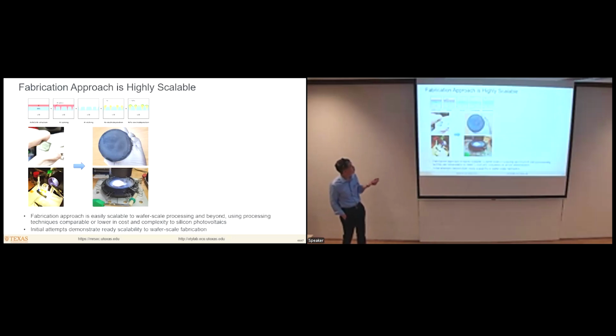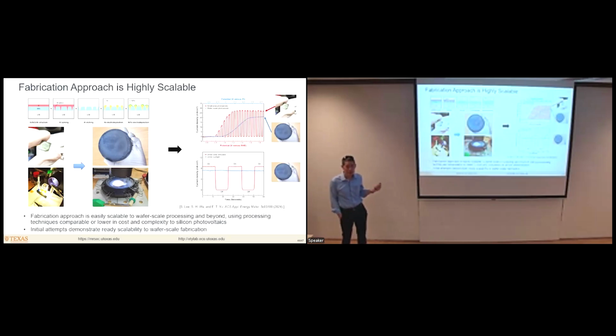So we were able to go quite easily from making devices that are kind of this size, which is what is typically reported in literature, to doing this on full wafers. In this case, this was a 4-inch wafer. Even without optimizing this at all, we were able to make at least okay wafer scale photoelectrodes. This is the current voltage characteristic, basically the LSV characteristic, of a full wafer photoanode compared to a small area photoanode. It's definitely not as good because this is less uniform than the small area, but that's certainly something that can be improved with probably moderate effort. You have very similar characteristics under both a large area simulator and in direct sunlight. The current is a little bit lower in direct sunlight because of shadowing effects in the apparatus.